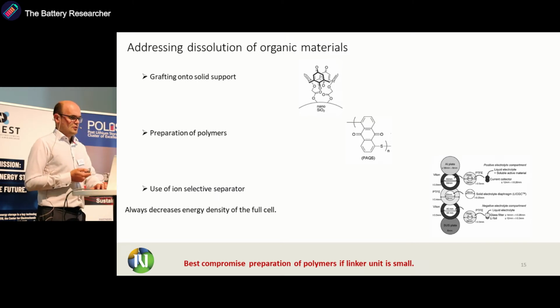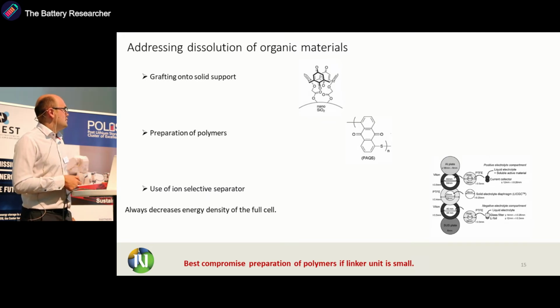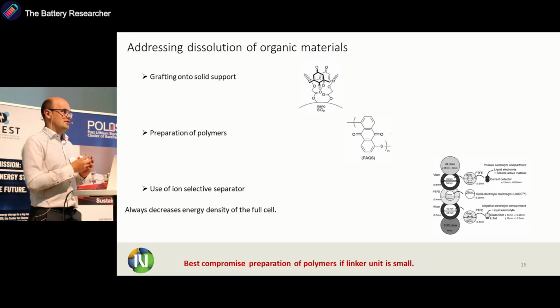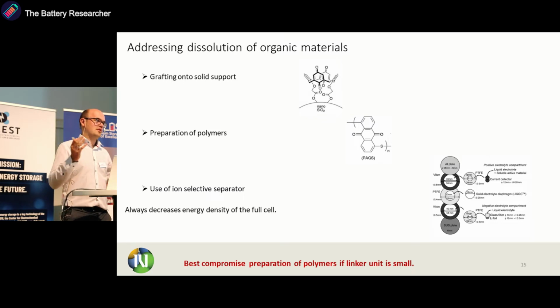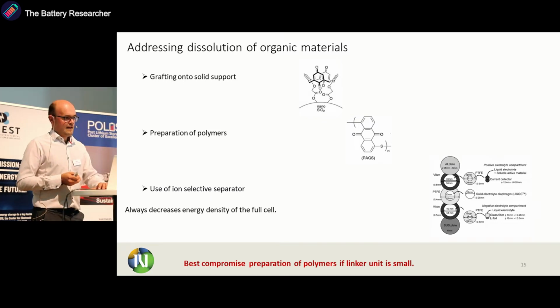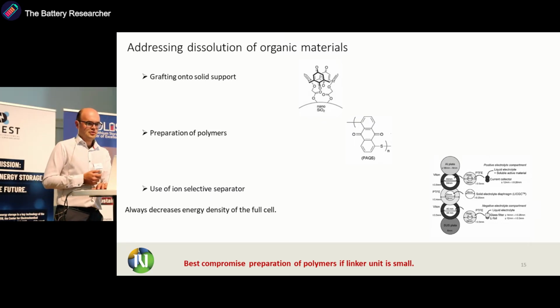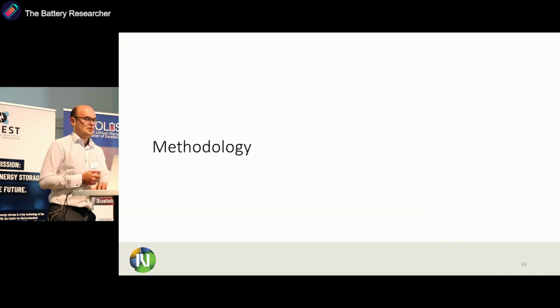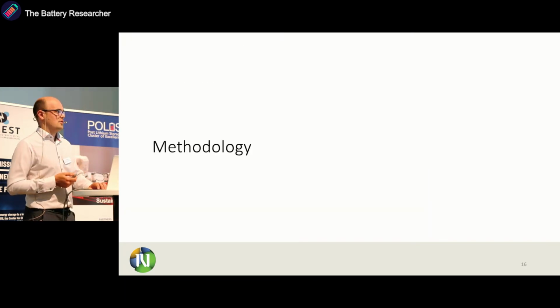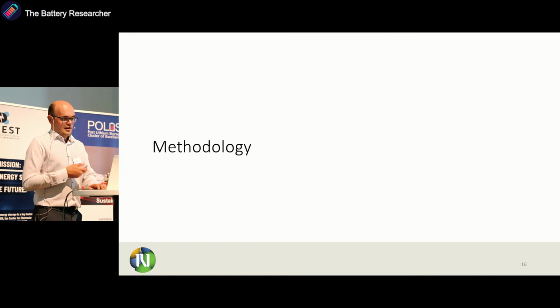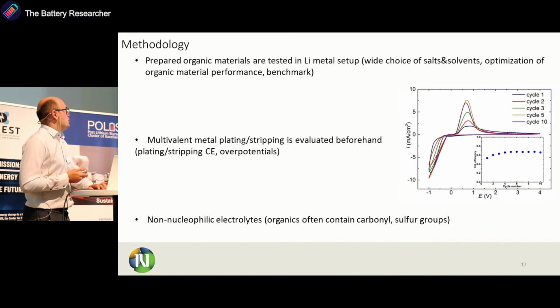So we found, and also the literature kind of agrees, that basically the best compromise is somehow to prepare polymers, but we have to keep in mind that this linker unit should be small. If this linker unit is large, we basically decrease their capacity too much. Now let's move to the actual research, and I'll spend just 2 slides on the methodology because I think it's quite important to get a feeling how we do research and what approaches we use.